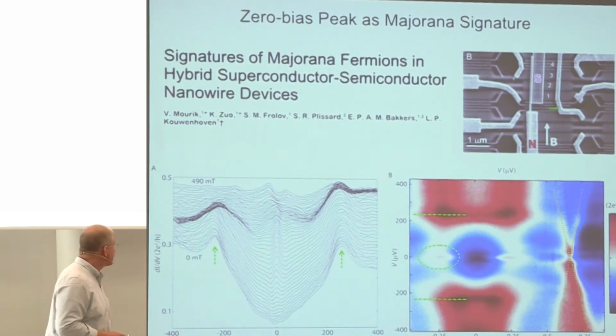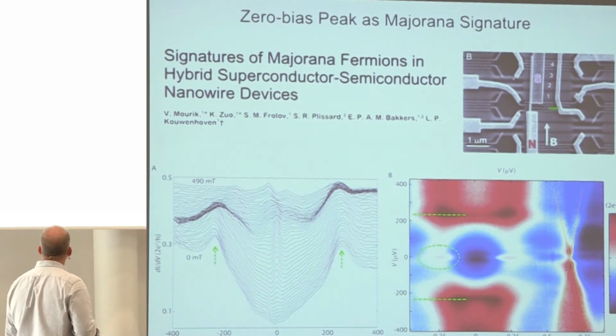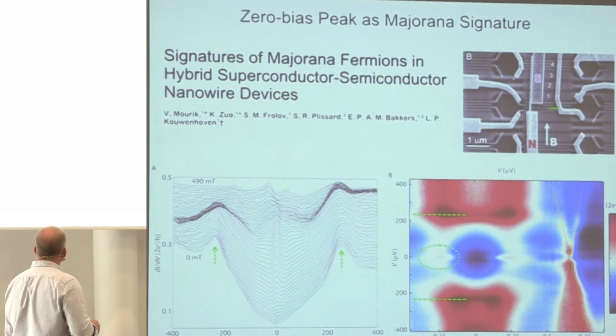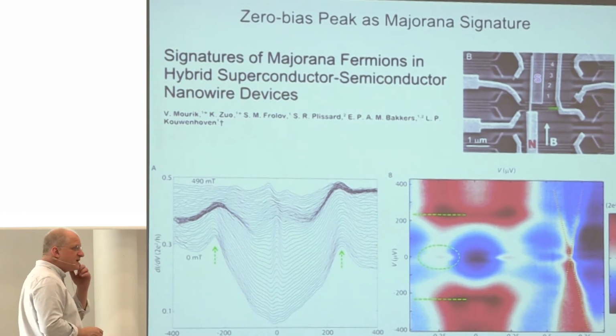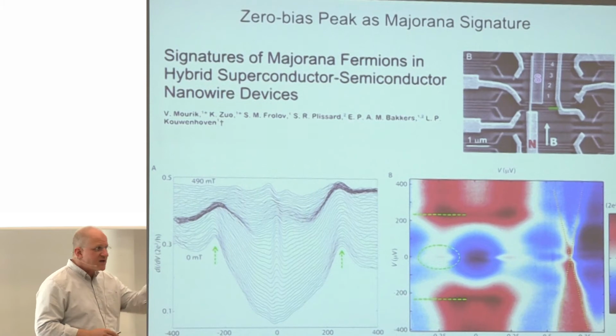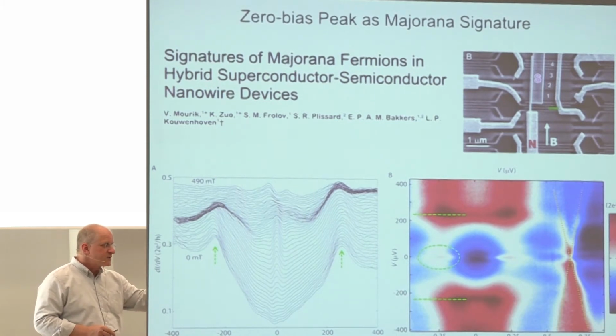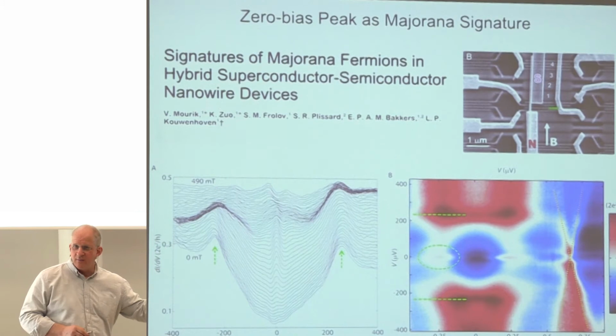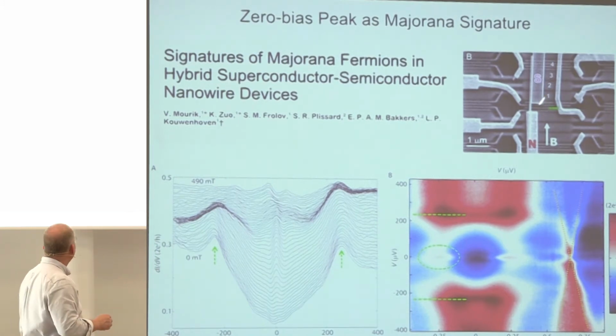So it's a pretty well-defined experimental signature, and it didn't take long after those papers for this beautiful experiment from Delft, from Leo Kouwenhoven's group, to appear, in which a superconductor, in this case niobium titanium nitride, was applied to an indium antimonide nanowire, making contact on one side. These gates that run underneath the wire could produce, right where my green spot is right now, the tunnel barrier, so that you could tunnel into the end of the wire and find out whether or not tunneling into the end of the wire was allowed at zero energy, indicating the presence of a Majorana zero mode at the end of this superconducting wire, this proximitized wire.